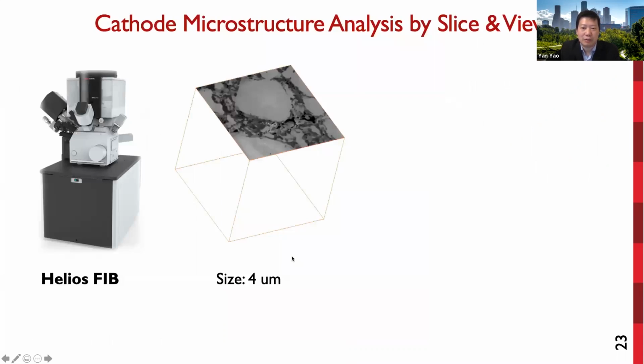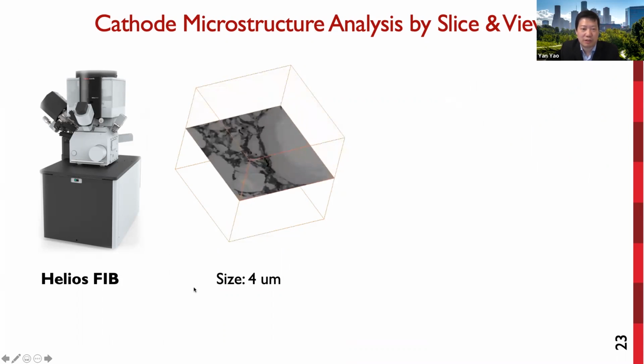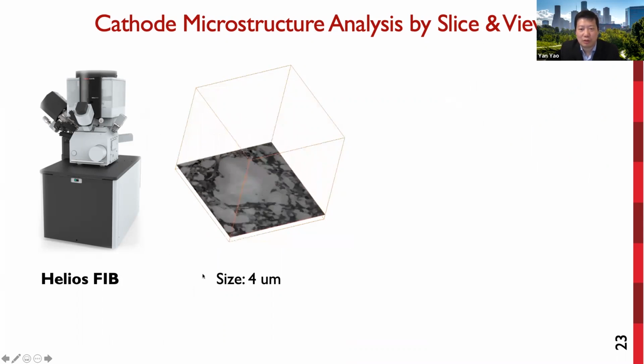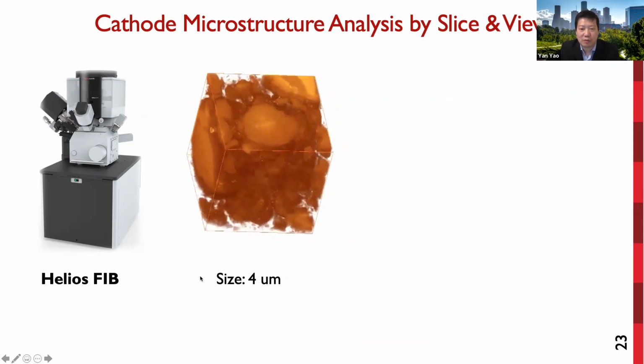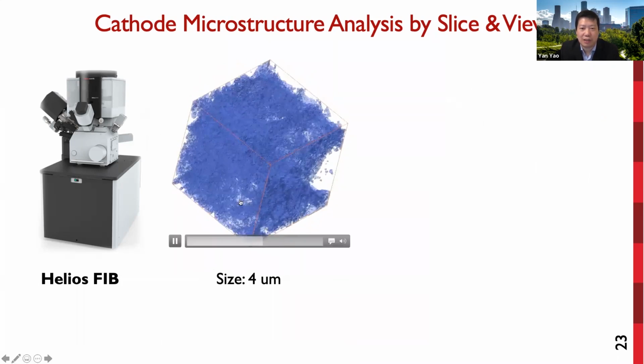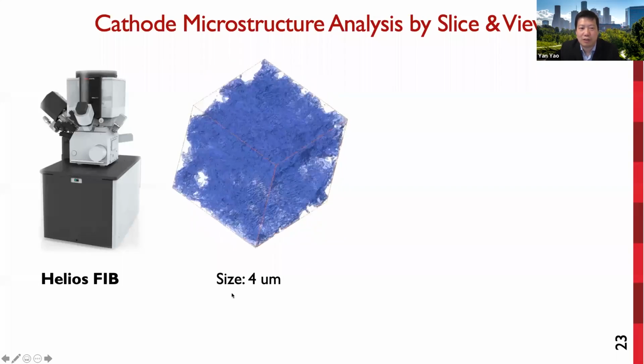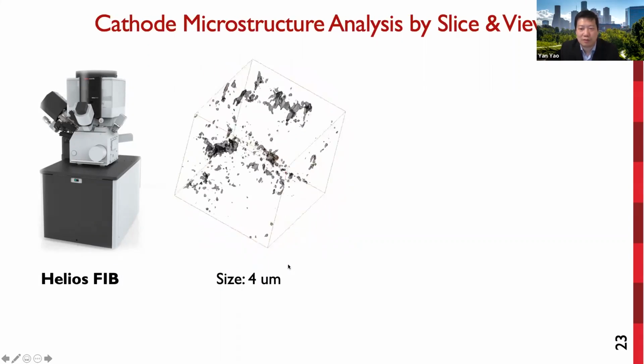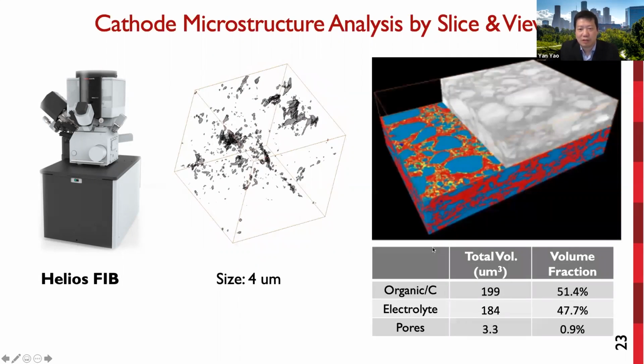So finally, we are also equipped with a focused ion beam SEM using the slice and view function. It can enable a reconstruction of the cathode composite. In this example is a PTO LPS freeze-milled sample. We can resolve the network of electrolyte. This is the PTO cathode, and we can also see the pore connectivity structure in the cathode composite. So segmentation of the 3D images provides information such as volume fraction and tortuosity. And we can also see the pores in this cathode composite are less than 1%.